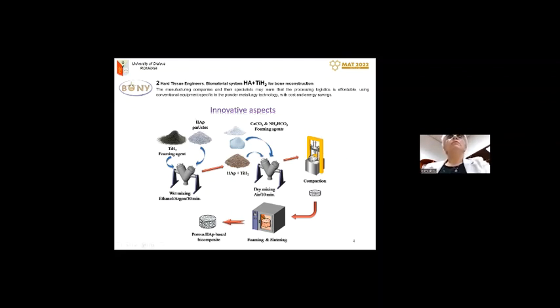So the matrix was hydroxyapatite. We tried two kinds of powders, nanometric and micrometric hydroxyapatite particles, which were mixed with titanium hydride powders, which were micronic. After the mixing, we also tried to improve the porosity by including other foaming agents, calcium carbonate and ammonium carbonate. The technology is quite simple, just mixing, compaction, and then sintering. But due to the combination of micronic and nanometric particles on one side, and the different kinds of foaming agents, we obtained different anisotropic structures, as you will see.